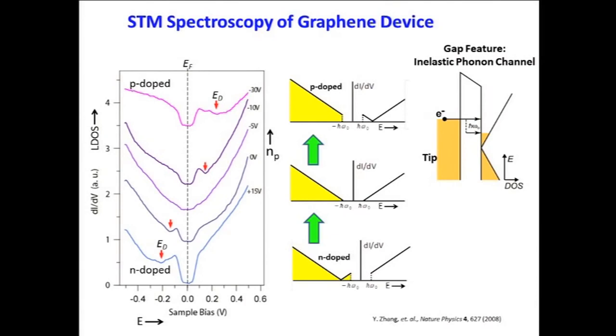Here, this little dip, that feature moves with gate voltage, so that tells us that it's a band structure feature, and in fact, that is due to the Dirac point. So you can see the Dirac point moving as you would expect as you p-dope the material. I just wanted to show you this and drag you through this because this is the baseline STM spectroscopy of graphene. And this is what we see after doing some elaborate tip calibration procedures.